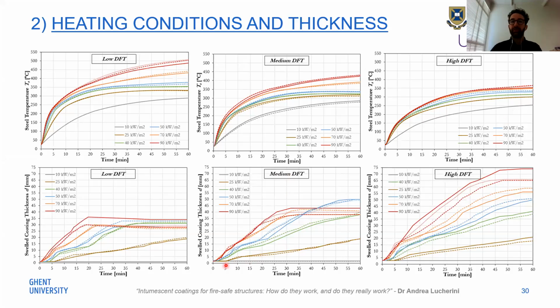In the case of medium, you can see that the coating starts swelling and at a certain point stops. In the case of high DFT, the coating swelled up to 70 millimeter, which is a lot. In the medium DFT, you can see that the swelling stopped around something between 40 and 50 millimeter. In the case of low DFT, the coating stopped around 30-35 millimeters. So you can already see that the coating could swell more for higher DFT, but this could be predicted because higher DFT means a higher amount of material, so you have more material that can swell.